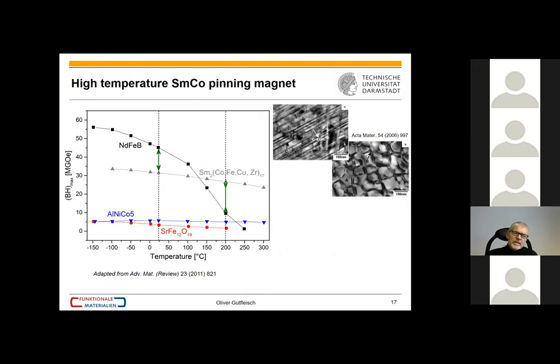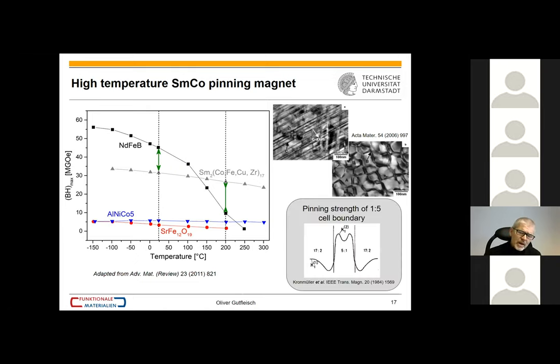Okay, now let me turn quickly to samarium cobalt. These are the classical pinning type magnets, but they are still full of surprises. You see here the typical cellular or diamond-like structure in these two crystallographic directions. And that is basically a system which is nanoscale regular by a decomposition reaction. And we couple here three ferromagnetic phases on the nanoscale together. And we have complex gradients of the anisotropy constant in these interfaces.